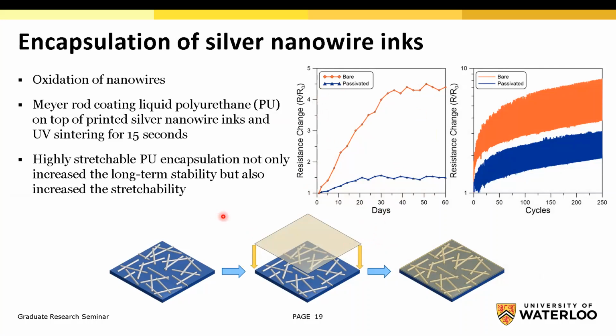And for this we found a very simple solution. We are Mayer rod coating a liquid polyurethane on top of silver nanowire inks and UV sintering for 15 seconds. With this industrially applicable, very simple method, you can see that the resistance change can be reduced. This orange plot is showing a bare silver nanowire ink, and the blue curve is showing the passivated, polyurethane coated one. You can see stretchability is also increased when we encapsulate silver nanowire inks with a stretchable polyurethane.